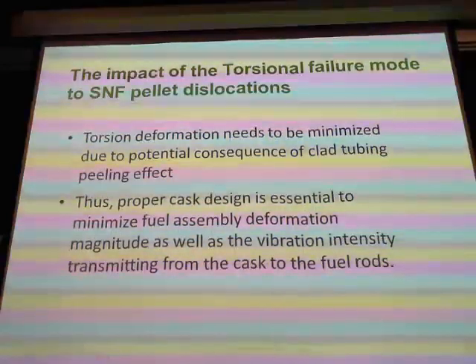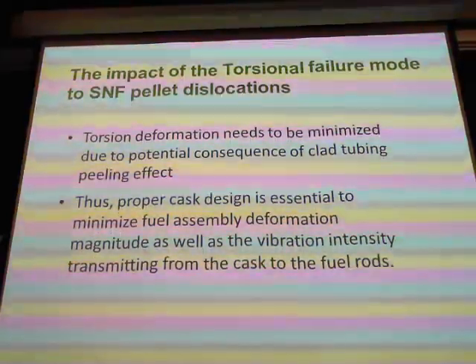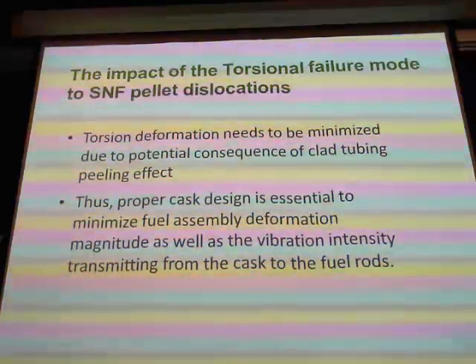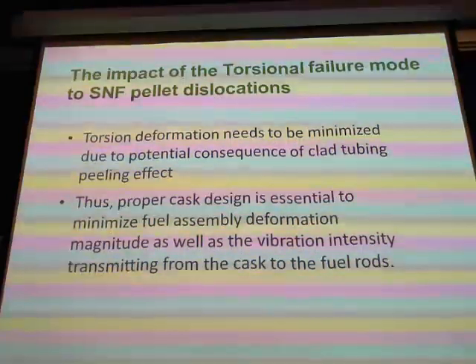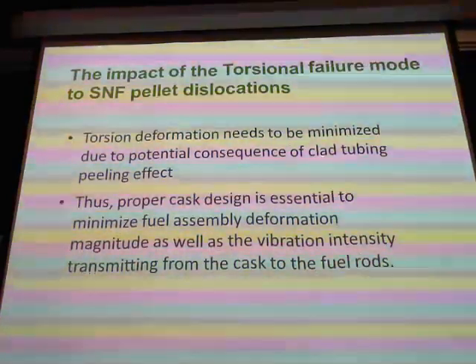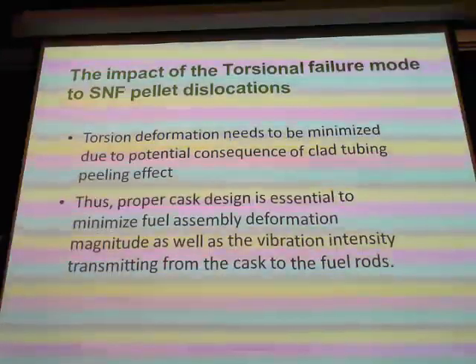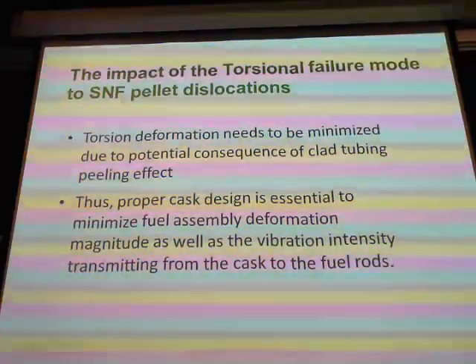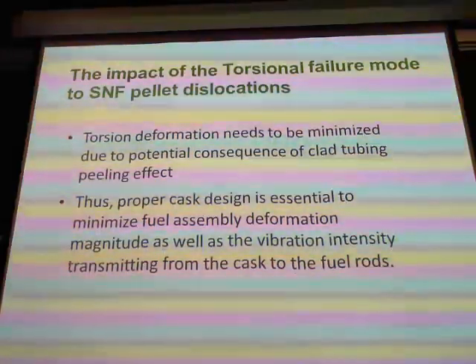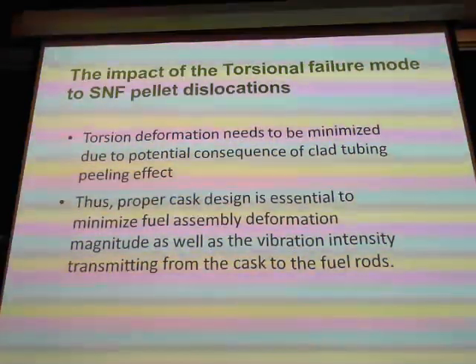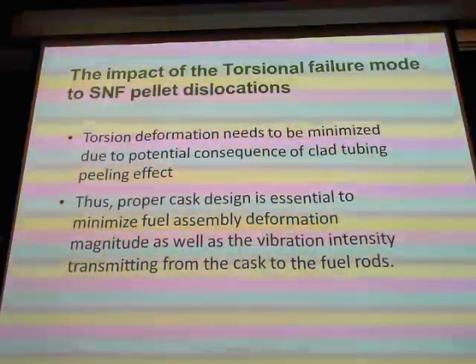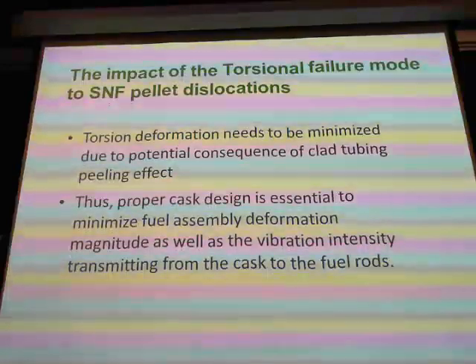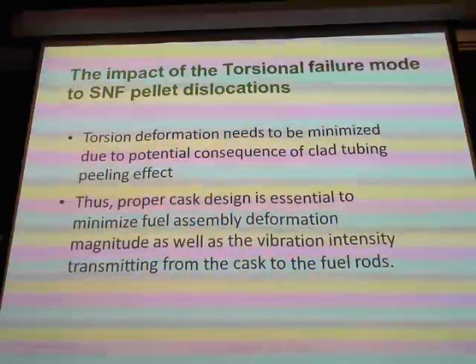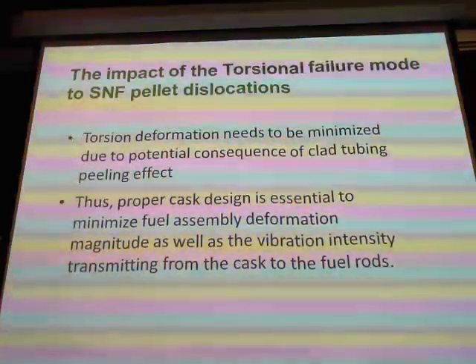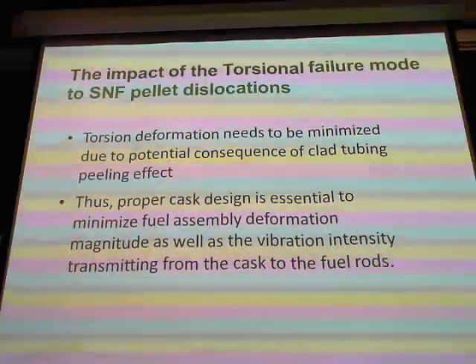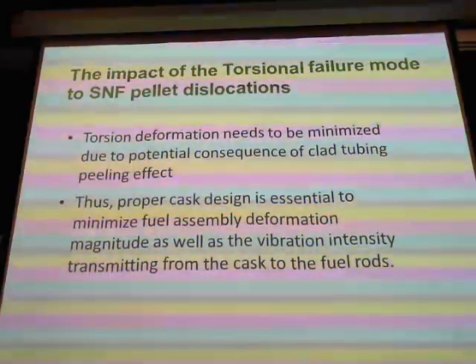So more fuel can come out, like a banana peel. More fuel will come out physically when you reach a critical mass, and then you have problems. So basically, we need to avoid torsion of the clad by all means, because clad is a very thin shell, and when you peel the skin, the fuel wouldn't be able to sustain. When you have bending, if the residual is right, the fuel would not come out. You have a few particles, that's a minus.